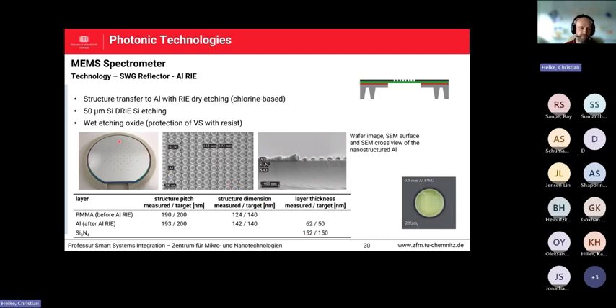And so you see here a wafer fabricated with all of these patterns. These ones here, which are much smaller, are the reflector apertures. All of the other ones are just test structures for process evaluation and characterization. And this is a SEM image in top view showing the 142 nanometer aluminum patches with a pitch of, let's say, 193 nanometers. So we are closer to the requirements after the patterning of the aluminum layer itself.